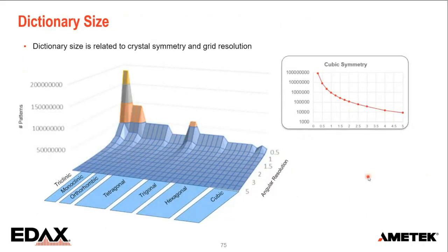Now, just a quick chart showing this dictionary size that I just mentioned. Here on the horizontal axis, we have the angular resolution, and that indicates how many patterns we need to cover all possible orientations. And as you can see, the lower the symmetry, the more patterns you need. You have more possibilities. But already for cubic, 10,000 to 100,000, a million, 10 million, 100 million points. So if you want 0.25 degree resolution, we're talking about 100 million possibilities. And that's already one step further than here. But we are already at 200 million for triclinic. So that's not very practical.